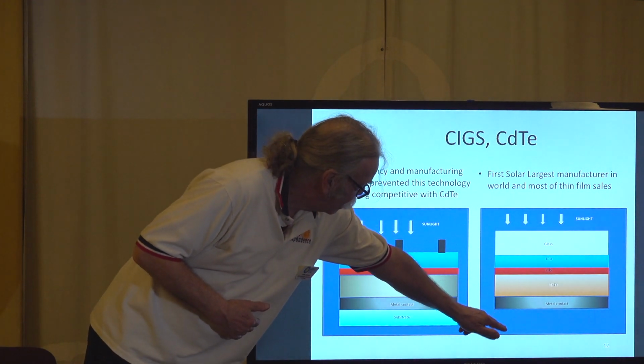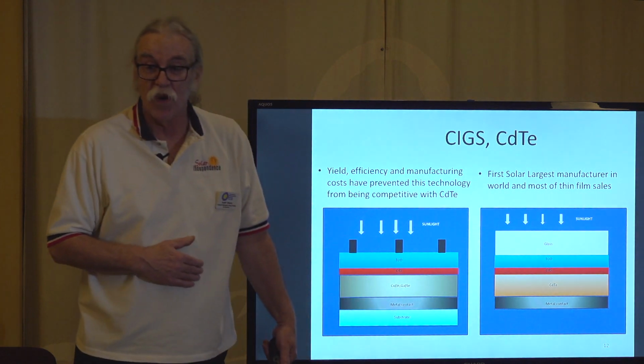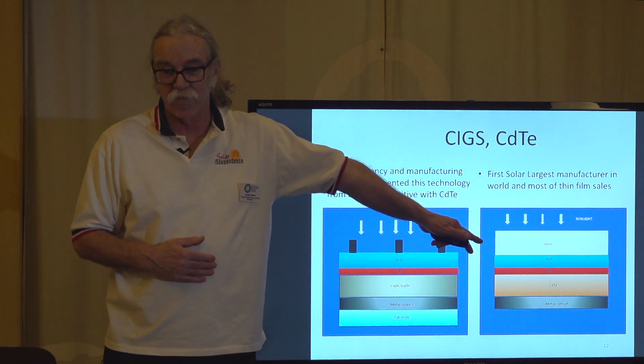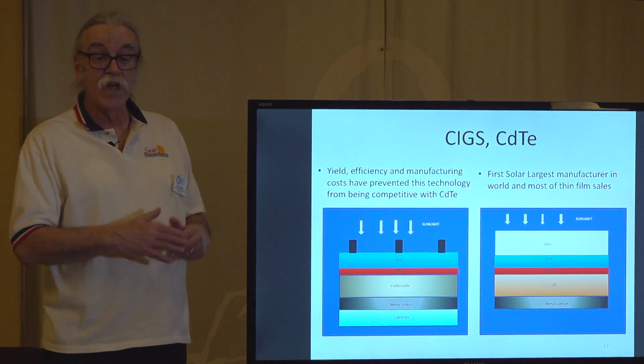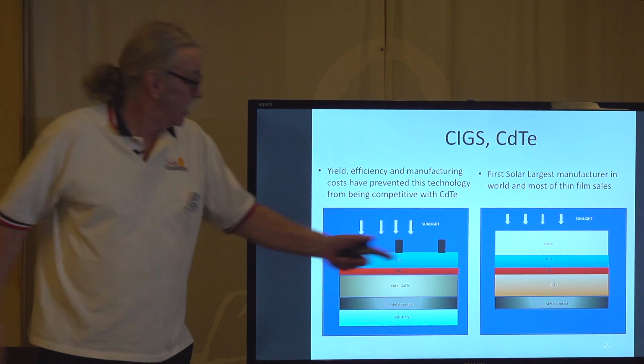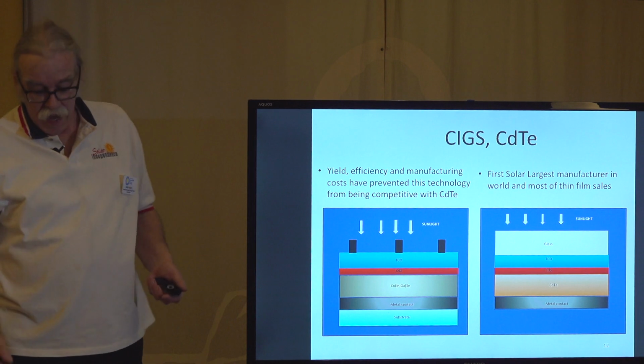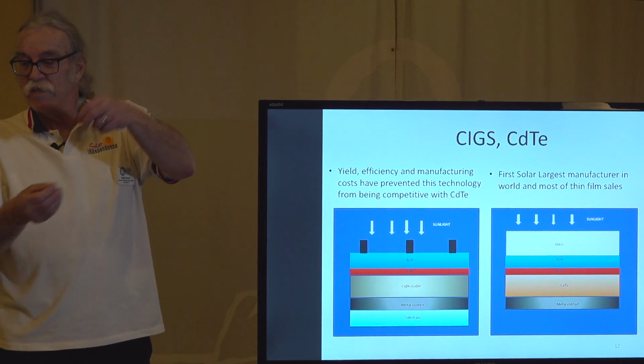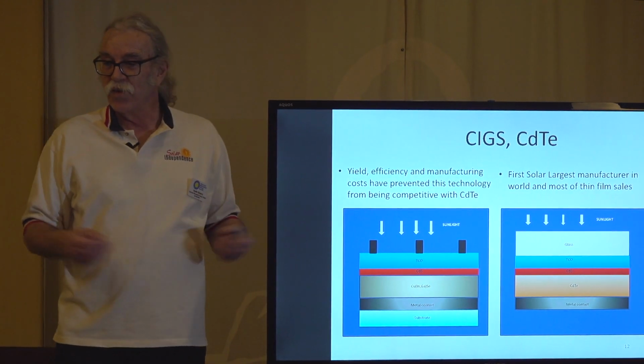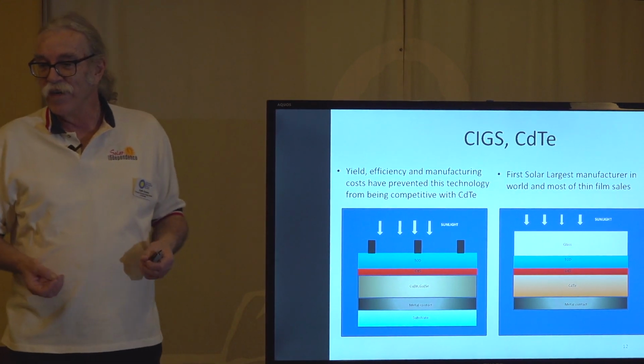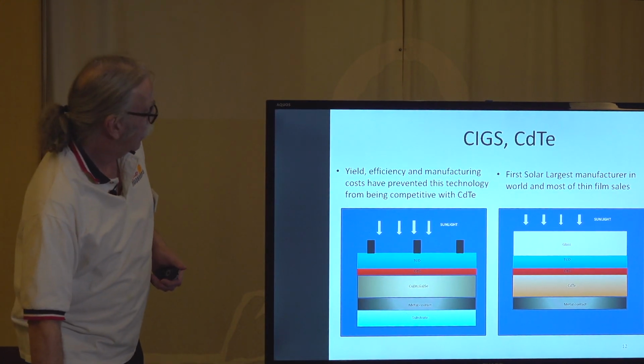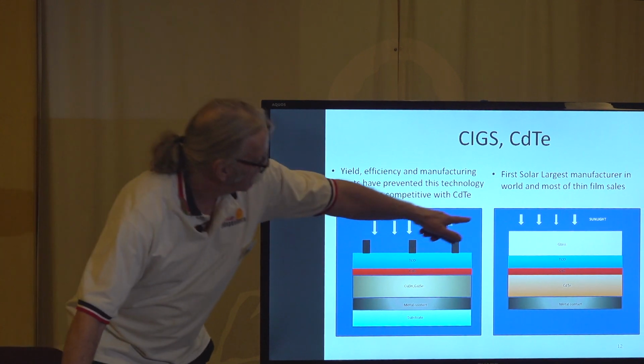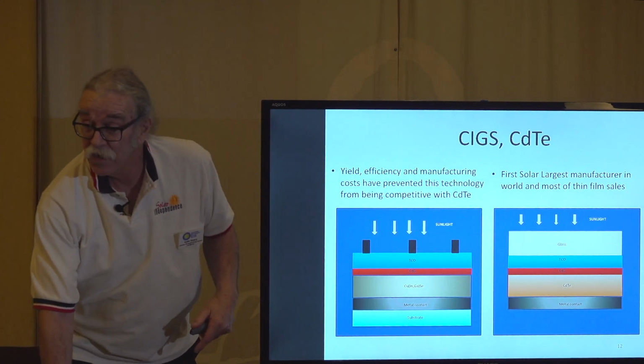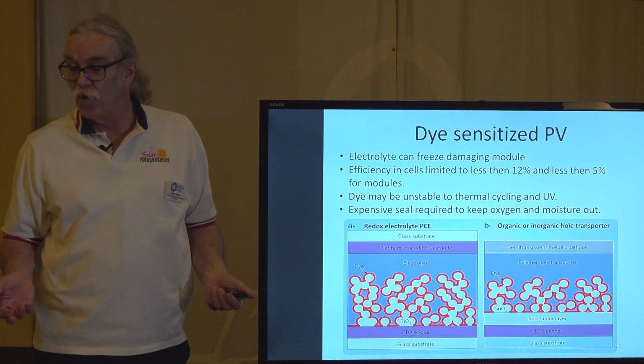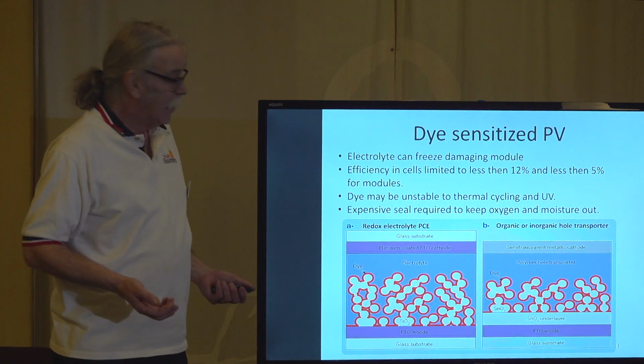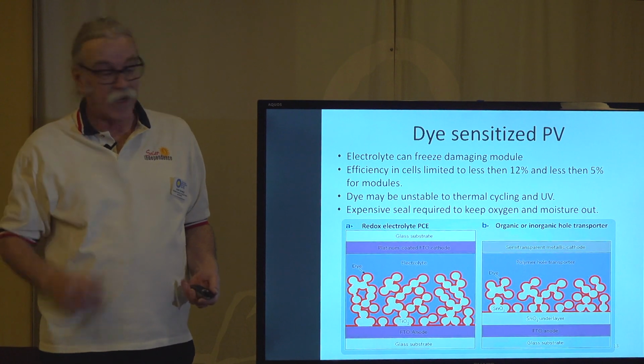And then you've got to have another piece of glass here to keep the whole thing from seeing any moisture, because this will degrade spontaneously in the presence of moisture. And so they've got to really seal it up. Golden Photon, which was in the business of cad telluride for a few years, actually put little desiccant between the two pieces of glass to try and keep the moisture out. And it turned out the desiccants blew the glass apart. And so it didn't work. And so what you have to do here is to basically have the glass edge seal sealed up really well. Again, you can't seal it perfectly. So how good is good enough? Well, that's what First Solar has been engineering.